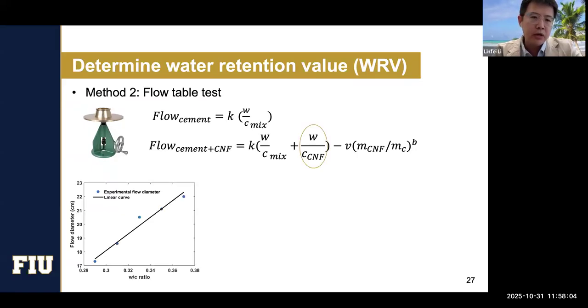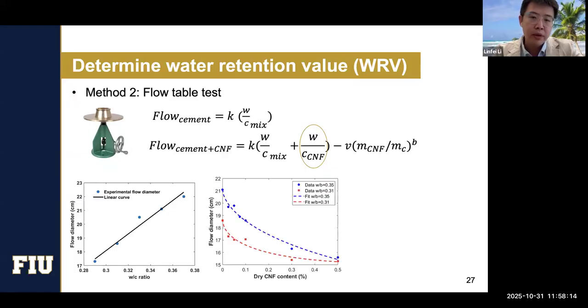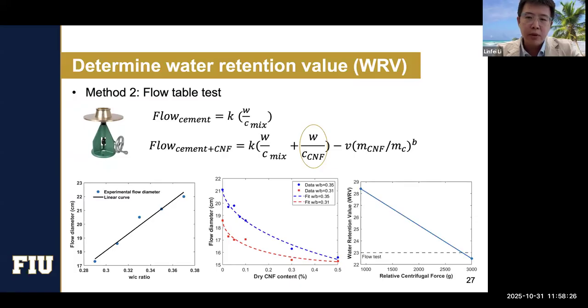So what we did first is a calibration using the flow table test, just for the cement with different water to cement ratios, and we incorporate the CNF. We quantify that as a dry CNF content with two different water cement ratios. We did the fitting on it. Finally, based on the equation we derived, we are able to quantify that the water retention value is around 23%. From this range, we can see that 23% is good at this moment.